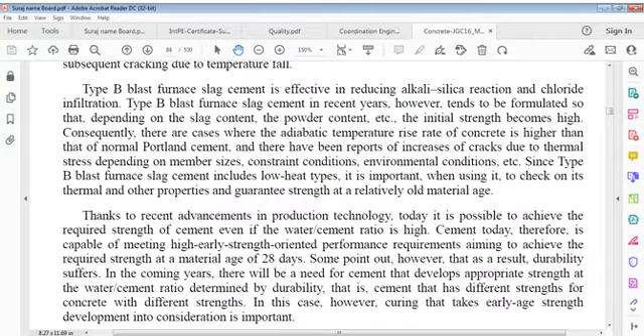At initial stage of cement hydration, BFS particles, blast furnace slag particles, are packed uniformly on surface of cement particles, which retard and decrease mutual combination of early hydration process products. Now, this is somewhat similar to effect of water reducers and increases fluidity of mortar. In other words, glass of SiO2 constituents of BFS particles reduce frictional force among particles.